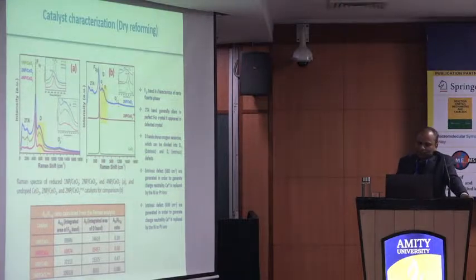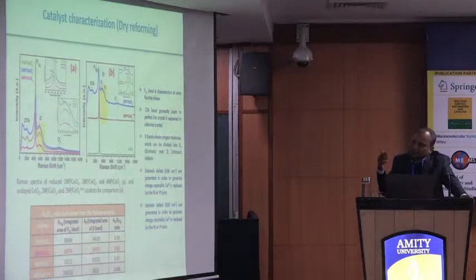Also, we have done some Raman spectra. You can see here from the Raman that the F2G band is shifted. That means platinum and nickel have been incorporated in the ceria lattice. Not only that, this catalyst is making more oxygen vacancy sites. You can see here we have also calculated the ratio, and we have found that for the 2NP ceria catalyst the ratio is the highest. That means it has the maximum number of oxygen vacancy sites.